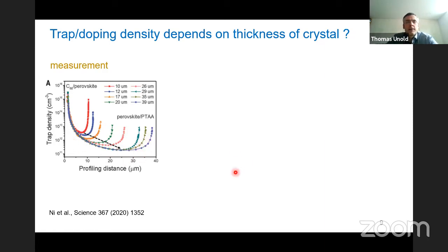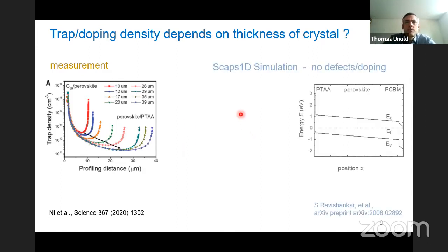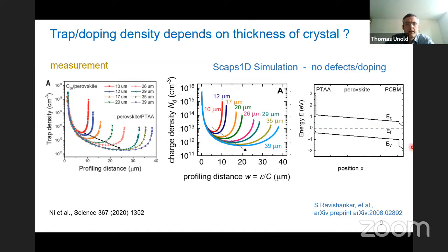And that's really a question. That was their conclusion: that the trap density or doping density depends on the thickness of the crystal. But if you think about it, it's a little hard to understand why that should be. And so what we did then is we took a relatively simple model, the SCAPS 1D drift diffusion model, open source, with the perovskite, a PTAA hole transport layer, and a PCBM type electron transport layer. And we simulated the same devices, so the same thicknesses, with no defects and no doping in there. And this is what we got. And you can, I think, immediately see it looks identical. It looks completely identical to their measurement results. And that is really surprising in a way and not easy to understand.